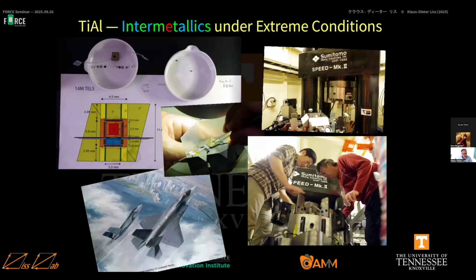Okay, let's now come to high pressure. Let's come to the topic. This is an example I want to give, just very briefly, where we have a titanium aluminide sample here in the center of a Kawai-type press. So a very similar press to the one you have, this Ichiban. And the sample size is this. It's relatively small. You see here 1.5 mm or maybe 2 millimeters across. And the other things inside here, this is a pressure medium, and you have heating elements. So with electric current going through these leads here, we have a heater, and we can heat up the material within that little sample volume.